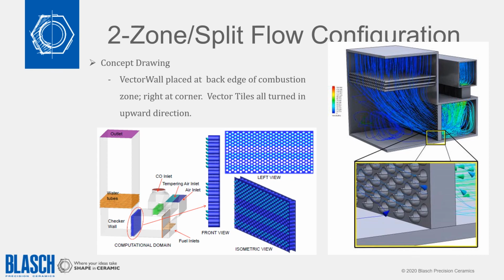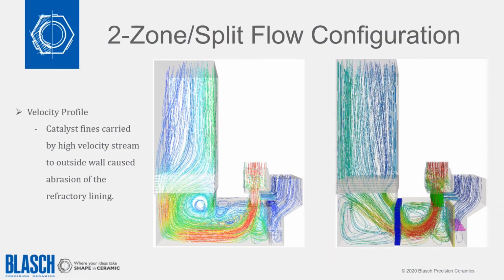We got some inquiries from some folks saying, we're having a problem with abrasion, as catalyst fines are entrained in here, so the refractory lining along the bottom and back walls is being abraded, and they're not getting the full effect of the convective heat transfer surface. So they wanted to know if we could use a VectorWall to attenuate the flow coming out of this combustion area.